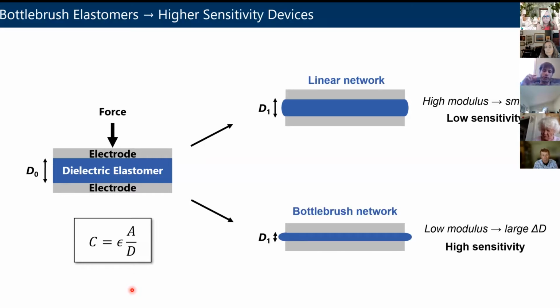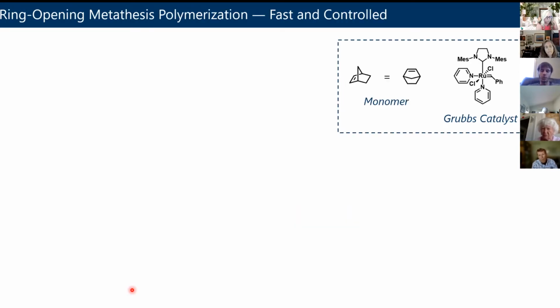If you put a special super soft elastomer in the middle, made up of these bottlebrush polymers, you'll be able to deform it more. It'll have a lower modulus or a lower stiffness. The thickness will change more, and you'll have a much higher sensitivity. So that's the idea. Now, for those of you like Mary that enjoy chemistry, you may like this slide. If you don't like chemistry, you can zone out for 30 seconds, but it's kind of neat the way that we make these materials.